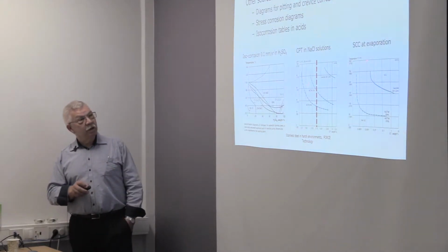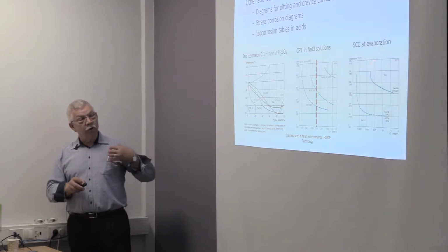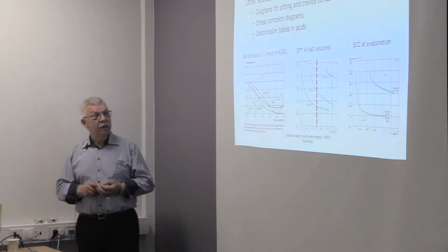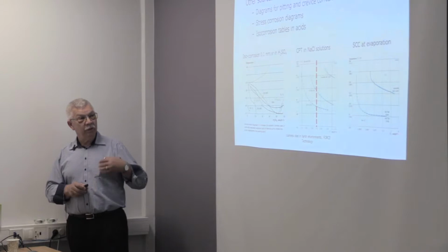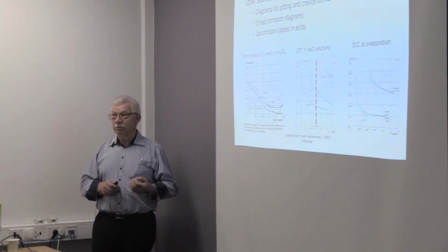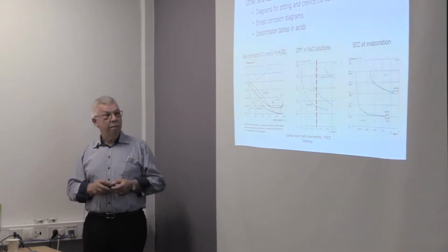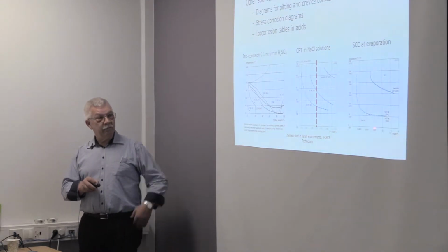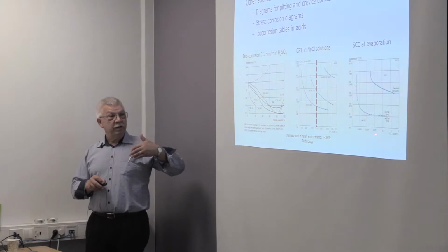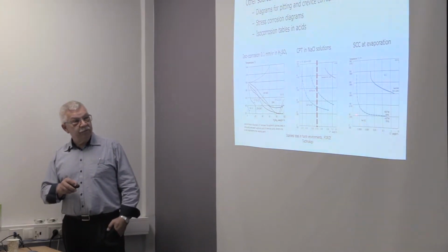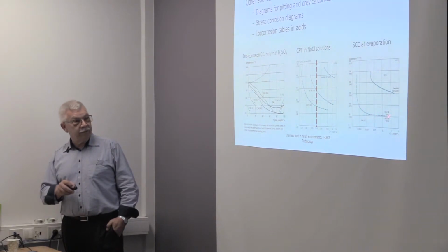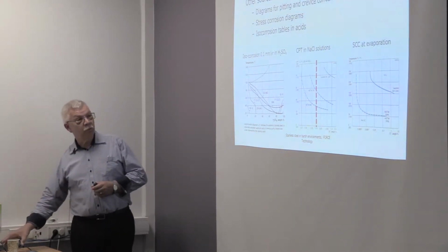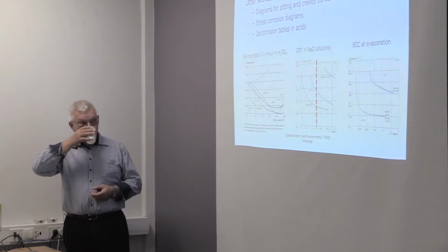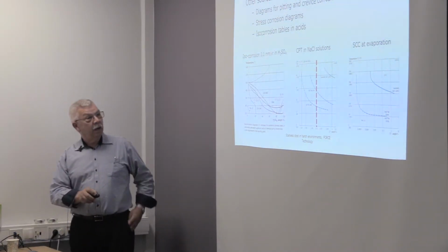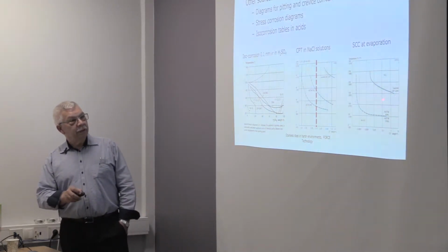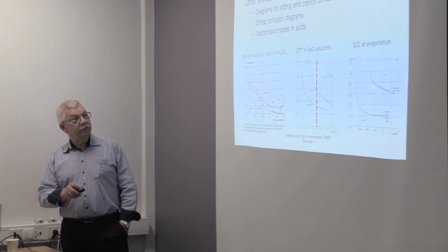And the same goes for testing for stress corrosion cracking, where we get not pits, but we get cracks growing into the material. And in fact, in the laboratory, we can have it growing as fast as 1 millimeter per day. So it would be very critical to have that kind of corrosion. And what we see in this diagram is that if we have evaporation, which will increase the chloride level, then we will not be able to go above some 50 to 60 degrees C before ordinary 304, 316 stainless steel will start to form cracks. And of course, higher alloy steel like the duplex stainless steel will be able to take a higher temperature before cracks will be seen.